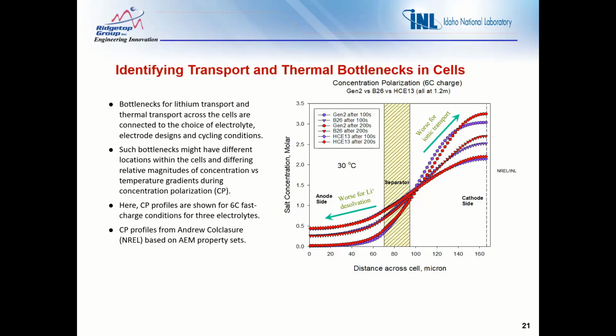What we see here on the left-hand side, where the anode is, is that these profiles get worse for lithium desolvation. And as we go to the right, through the separator and into the cathode side, what happens there becomes much worse for ionic transport. So these are the things you have to pay attention to when designing electrolytes for particular applications. And it has to be done holistically with the cell materials, like the electrodes and the separator, because everything works in concert and is interdependent. Okay, next slide.